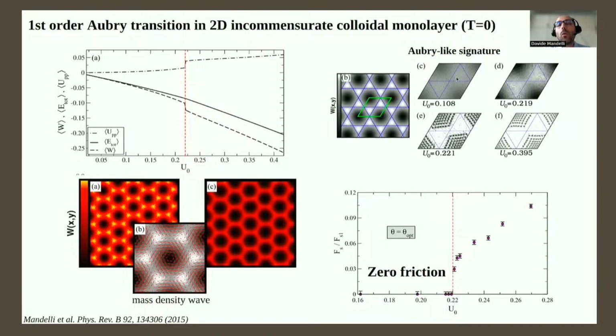So what I'm showing is one primitive cell of the substrate potential, and I have folded the positions of all the particles within the primitive cell. The region within these triangles corresponds to the maximum of the substrate. As you can see, as the substrate potential is increased above the critical point, this region becomes completely avoided. One main difference with respect to the Aubry transition is that in this case, the transition is first order instead of second order. Now, all these results were obtained at zero temperature.